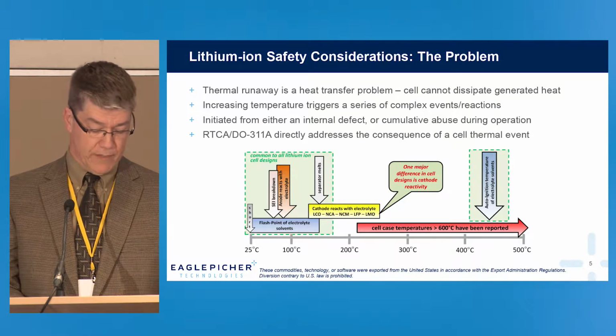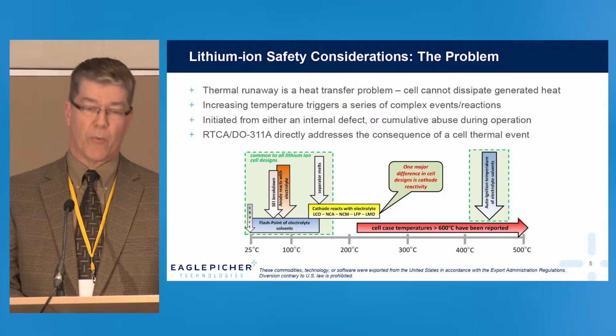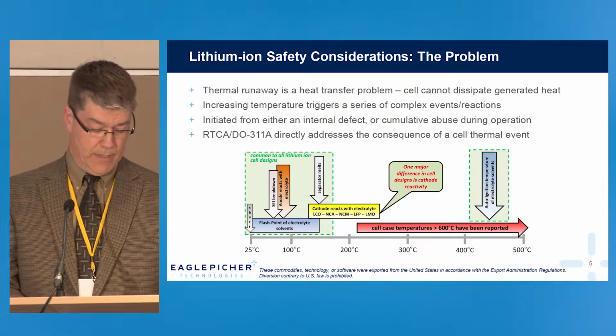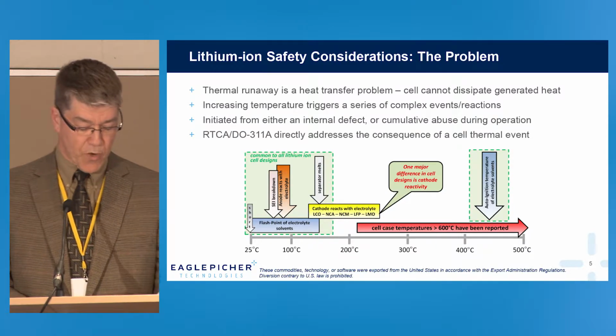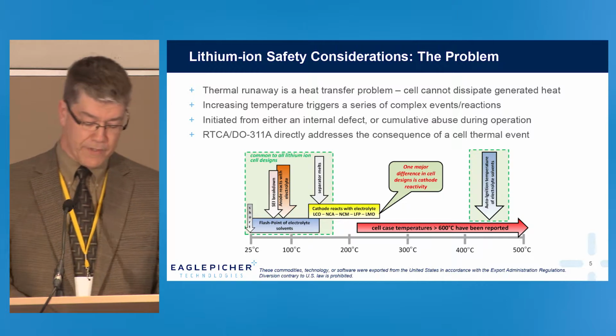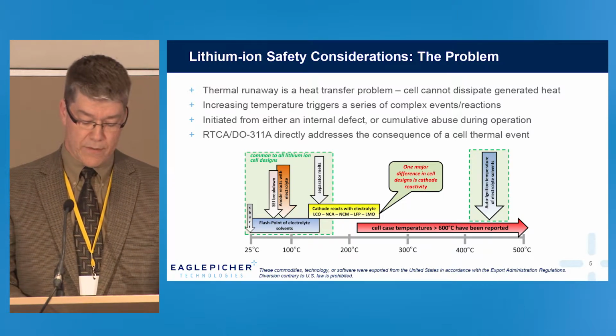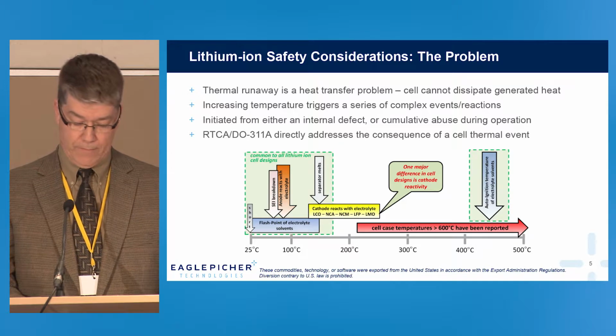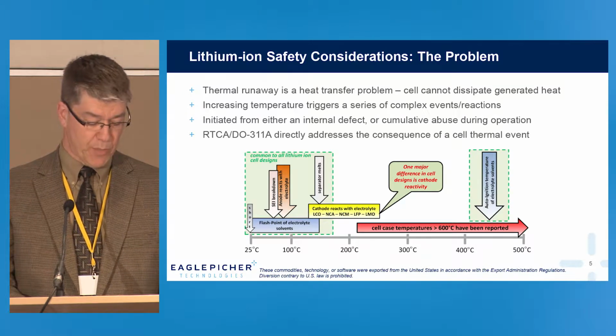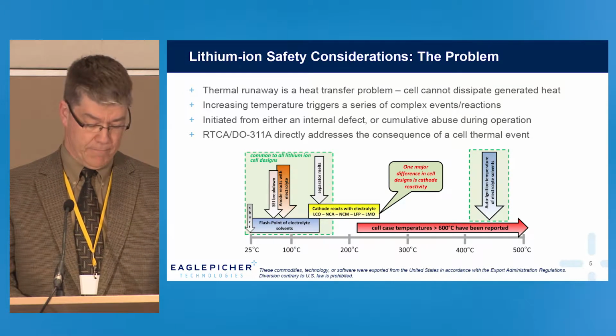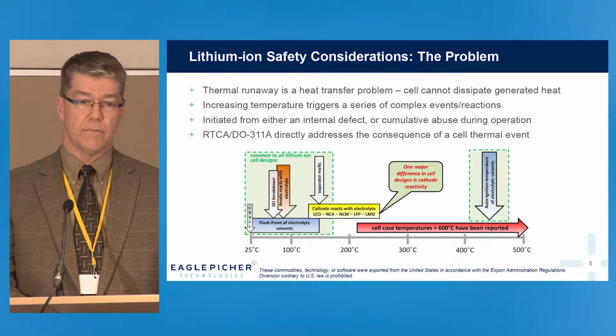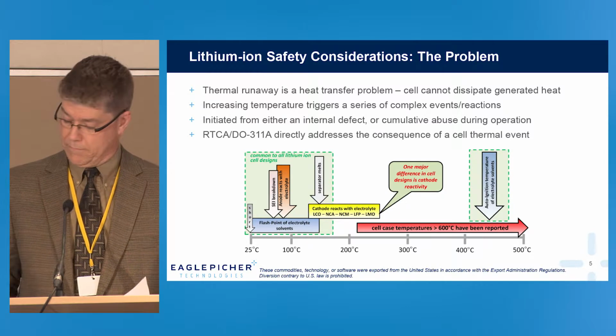Degradation can result from a cell assembly defect, or can be instigated from operational abuse. So the cell temperature continues to rise, leading to cell venting of the emissions and at times particulate debris, with cell temperatures rapidly approaching 600 degrees C, which can then auto-ignite the electrolyte solvents.